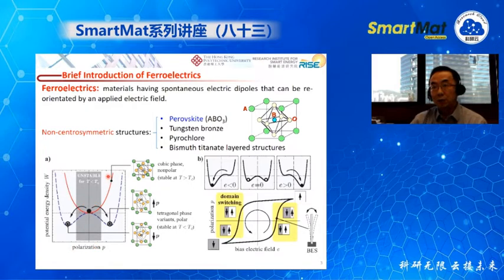At a high temperature above the Curie temperature, the potential energy as a function of polarization shows a parabolic curve. So the minimum energy corresponds to zero polarization, when the positive ions and negative ions are located at the same position. Now, when the temperature is below the Curie temperature, the potential well becomes a double well. So now you can see that for the minimum energy, the corresponding polarization is non-zero. So there is a relative shift of the positive ions and the negative ions.